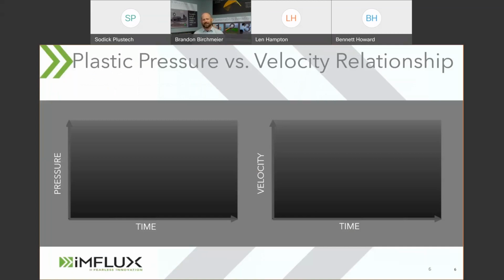Next thing we're going to talk about is the pressure versus velocity relationship. And this is really important. Like I mentioned in the prior slides, in your conventional process today, you're telling the machine at which velocity you want to inject that. And the pressure is a result of that velocity until you transfer. So you get a relationship that looks very much like so, right? Your machine's getting up to that constant velocity. As it maintains it, the pressure in the system continues to climb until you transfer. The velocity drops out during our pack and hold phase.